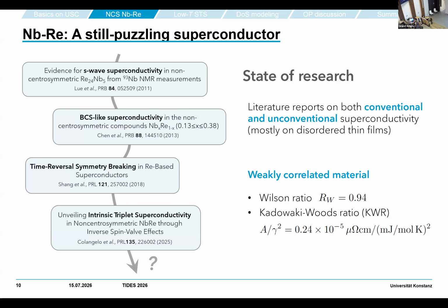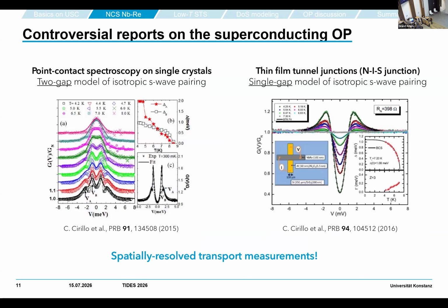When we test for indications of electronic order, we are in the situation of weakly correlated materials, so we don't have strong electronic correlations. For transport measurements, there is a group, Carla Cirillo and Salerno, who investigate these systems intensively. What she found is that using point contact spectroscopy on single crystals, with roughly 10 nanometer size point contacts, she finds indications for two gaps with S-wave symmetry. But when studying extended crossbar tunnel junctions, it all looks like a single S-wave, a bit rounded, consistent with a single isotropic order parameter.